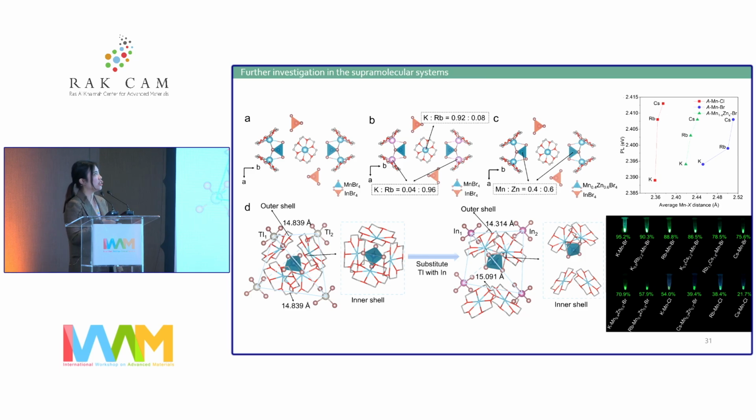You can also see how it changes the emission, which generally doesn't happen in the manganese system: if the bond length is slightly shorter, that further affects the ligand field strength and then changes the emission.